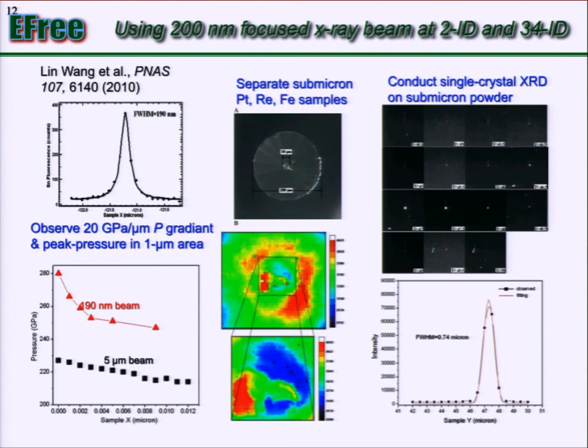Another very interesting application is that in the past, at high pressure, you could only do polycrystalline diffraction, while single crystal X-ray diffraction gives you a much better result. But if you have a sample at high pressure, it will be crushed. You can re-synthesize the sample at a high pressure, but usually you only get micron size. In this case, you can pick a small crystal and do a micron size single crystal diffraction.